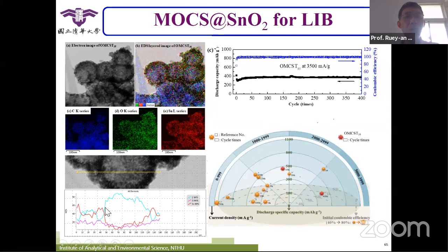You can see that when you use the line profile, this one is the carbon and this one is the tin. Inside, no tin gets in, but outside we can see a high concentration of tin, which means the tin stays outside. We use this for lithium batteries as an application. Our value is here, and you will always see it is much higher than the reported data.